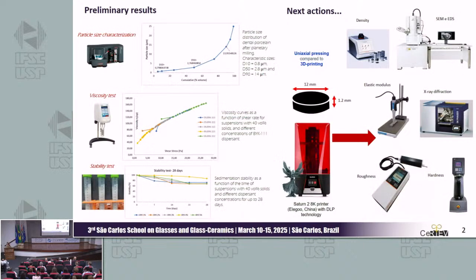There are preliminary results from the particle size characterization, the viscosity test, and the stability test. The best suspension was chosen for the printing tests. In the next steps, uniaxial pressed specimens will be compared to printed ones, evaluating density, elastic modulus, roughness, hardness, X-ray diffraction, SEM, and EDS. Thank you for your attention.